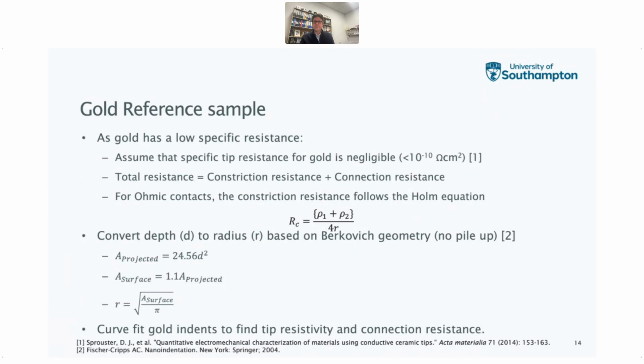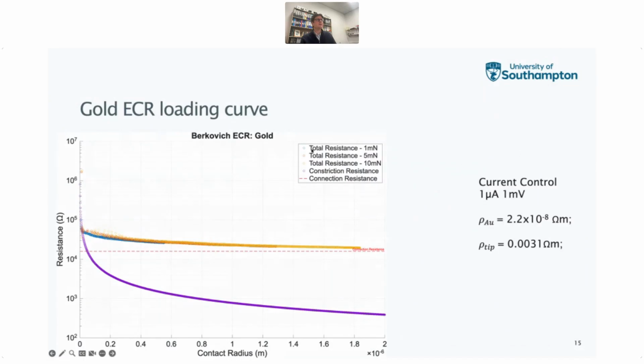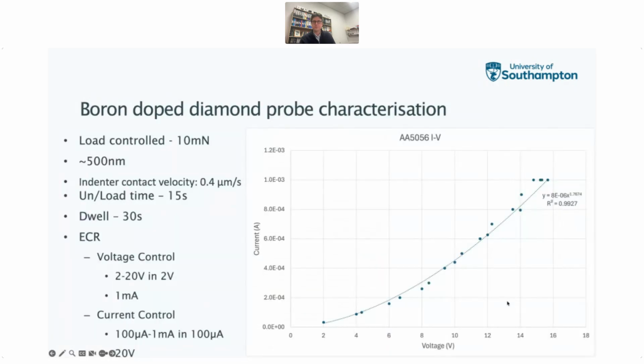Because we know our Berkovich geometry, we can then calculate the projected area based on the depth of the contact and convert that to a surface area, and then get an estimate of that contact radius and try and fit our total resistance to the tip resistivity and connection resistance. So as we then move the indenter through a series of indents at 1 millinewton up to 5 millinewtons and then 10 millinewtons, we can start plotting the idealized Holm resistance, the spreading resistance, the constriction resistance, and then get an idea of our connection resistance and indeed the resistivity of our tip.